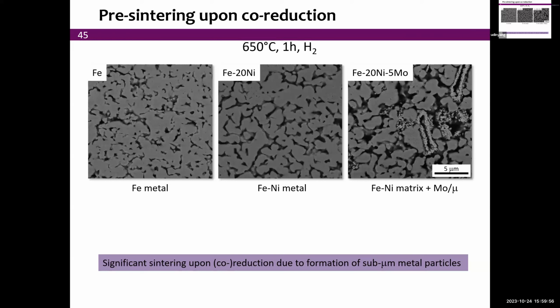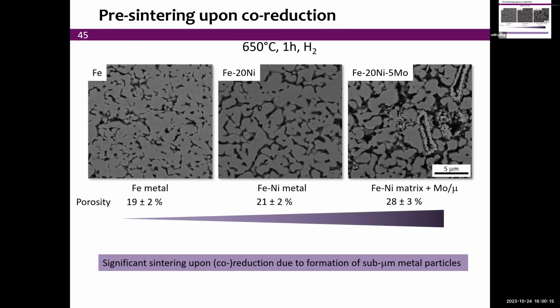We have not yet gone to the really high temperature to finish them off, but there is a significant sintering upon this co-reduction and homogenization of the material into sub-micron metal particles that are still independent and not yet fully sintered. And the black is the open structure. And so we go from about 19% porosity to about 28% porosity. You see also other phases here, which are due to the presence of molybdenum.